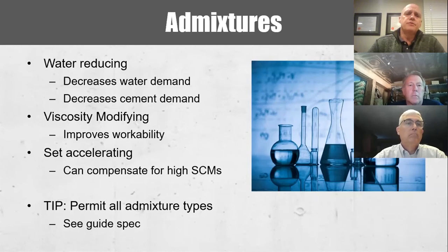Viscosity modifying admixtures improve workability. Again, mostly, there's not a huge carbon footprint reduction as a result of that, but anything you can do to make concrete more workable means less water that is needed in concrete, meaning less cement generally. Set accelerating admixtures are important only because high volumes of supplementary cementing materials often cause some set delays for concrete and strength gain delays. And so having these set accelerators can offset some of that delay in using high volumes of supplementary cementing materials. Again, the tip here is really to permit all admixture types. Don't try to limit the use of admixtures because they're so important in efficient concrete construction, and see the guide spec on recommendations there.